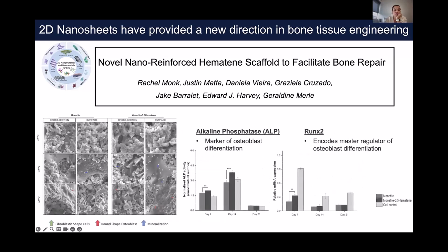And indeed, we show that here you have the cross-section and the surface of the monetite itself, and here it's when doped with hematene. So here you have the cross-section and the surface, and here you're showing some mineralization, and you can see some cells and also some extracellular matrix already formed into the cement. And you can see the expression pattern. We measured alkaline phosphatase, which is an early marker of osteoblast differentiation. It was improved, upregulated in the presence of hematene.